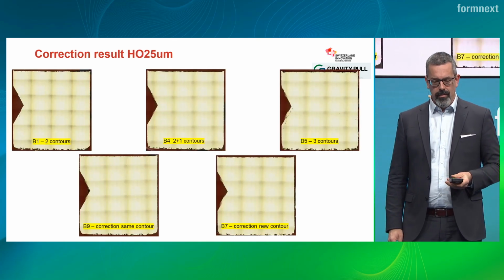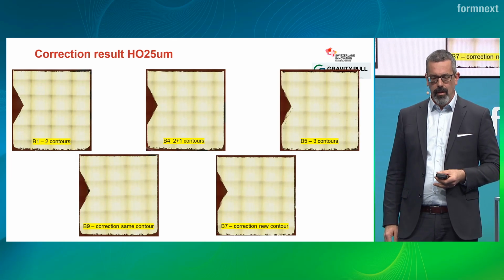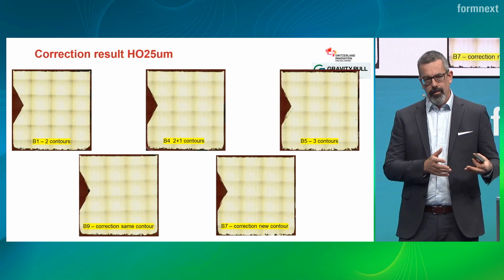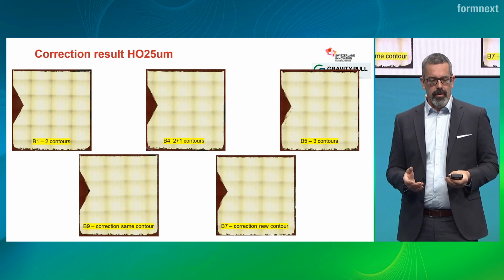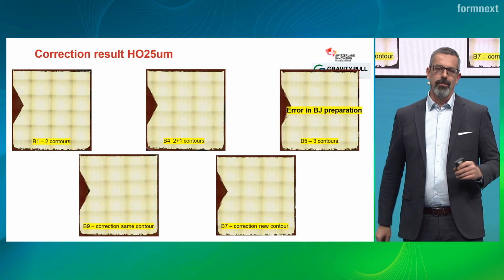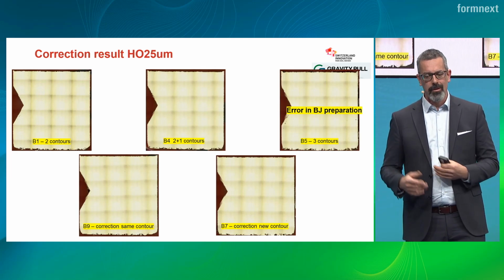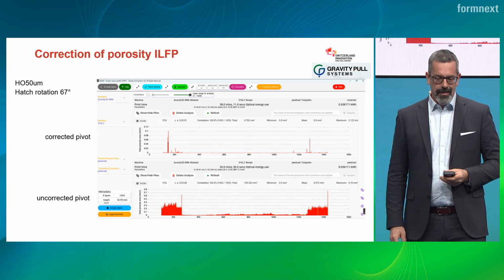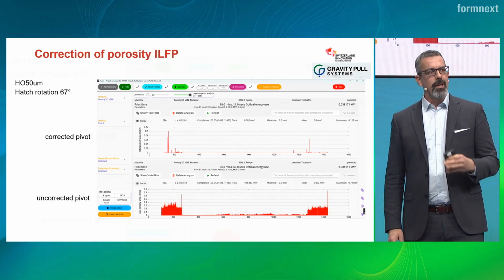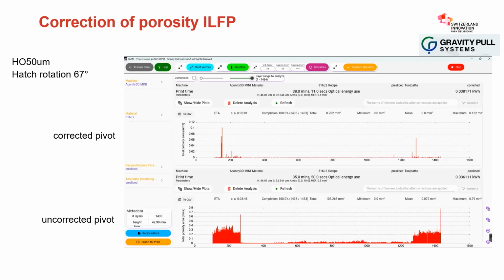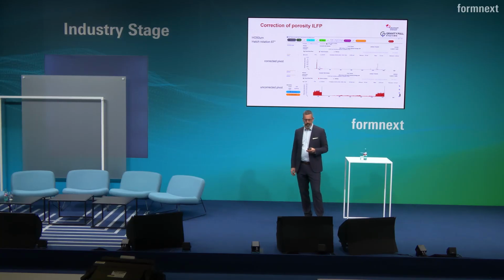We can do the test in practice, so there are several correction possibilities. So an added contour, a fraction of a contour, and so on in different orders, several recipes. All were successful except for this one, but there was an error that we could track that was coming from outside the algorithm. Yes, so it works. Now we apply this correction algorithm to this pivot mechanism. And you see the difference between the uncorrected and the corrected pivot in the predicted porosity is quite striking. And they carry the scale, it's different. So there might be some peaks left in the upper image, the corrected version, but it's much lower than in the one below.